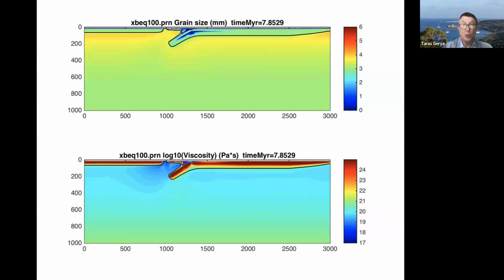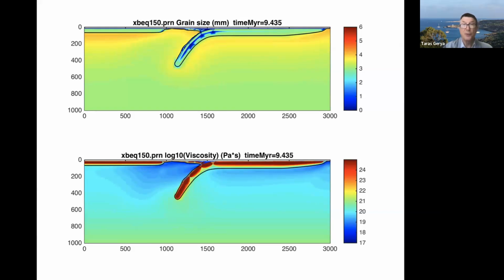What started to happen afterward was quite surprising when we saw the results of these numerical experiments, because we started to observe non-uniform deformation of subducting slabs. Instead of being subjected to uniform grain size reduction in the lower middle plane of subducting slabs and just gentle uniform bending, what started to happen is this segmentation. Essentially, deformation on the top of the slab focuses in the region of development of normal faults, and underneath these regions you see the segments of intense grain size reduction, which have triangular shapes, and they are breaking the slab into individual segments, with the length of these segments being proportional to the age of the slab. So we started to see this segmentation process, which has never been suggested for subducting slabs.